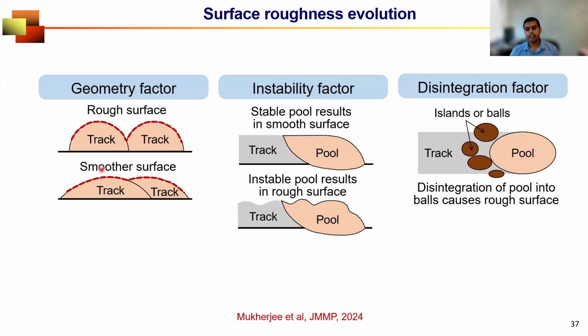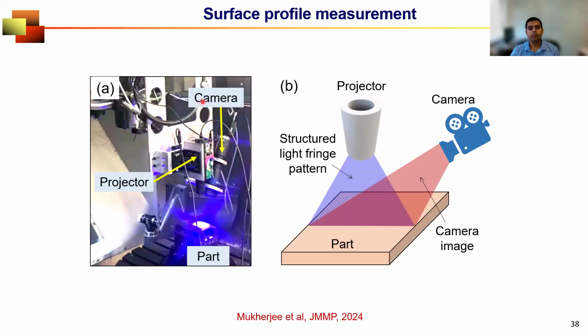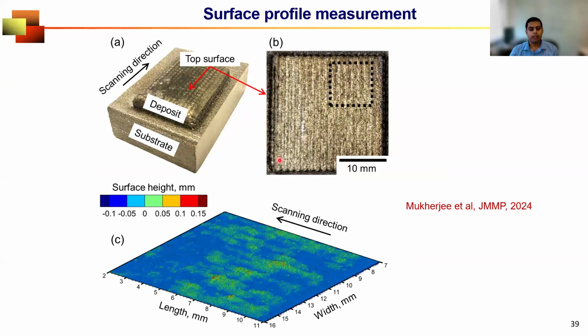What we did, we identified scientifically why surface roughness forms, and we came up with three different factors. A geometric factor that talks about how the tracks are deposited, an instability factor, whether the molten pool is continuous or discontinuous, and then whether the molten pool will be uniform or disintegrate into small balls and create surface roughness. All these things we calculated, and in parallel we also measured the surface roughness using a surface measurement method on this campus. And then we got the entire picture of the surface profile representing the surface roughness.